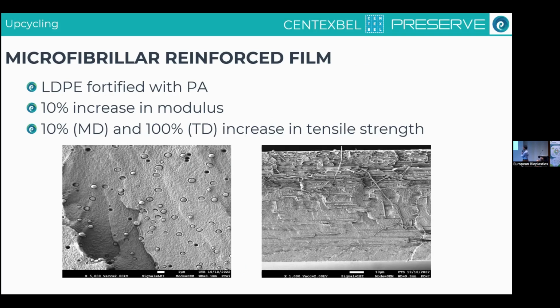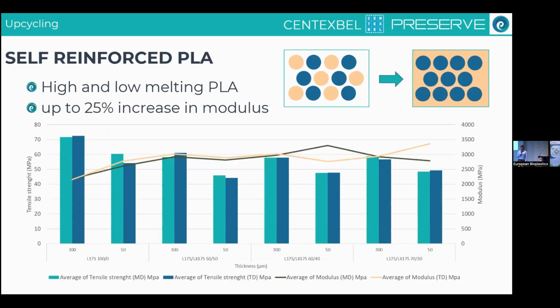You will see in the machine direction, they are really elongated, and you get a kind of composite material made from a matrix of polyethylene and a reinforcement of polyamides. This resulted in an increase of 10% in the modulus and an increase of 10 to 100% in tensile strength, thanks to the addition of the small fraction of polyamide.